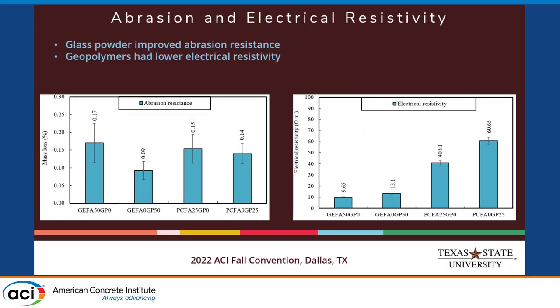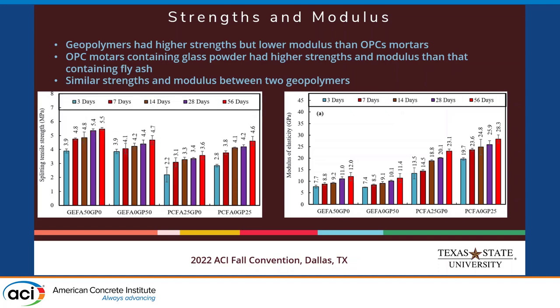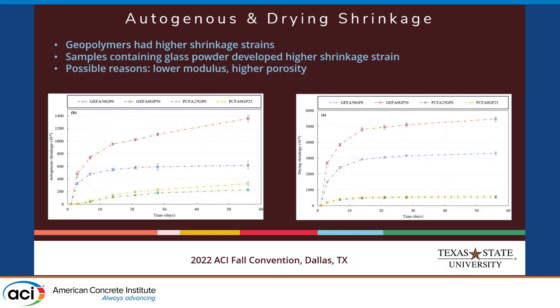For the abrasion test, adding glass powder improves abrasion resistance a little bit, but we still need to do more tests. For the electrical resistivity test, geopolymer-based mixtures had lower electrical resistivity — that's because you have more liquid and more ions. For the strength test: basically, we can produce geopolymer at very high strength with glass powder, but the elastic modulus will be lower than the conventional Portland cement-based mortars. Same for the split tensile strength — the strength can be higher than conventional Portland cement-based mortars.